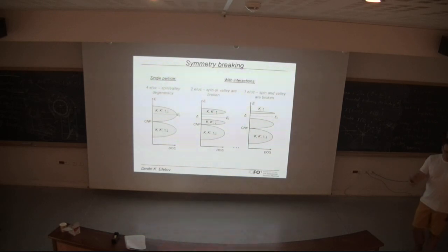Okay, but now with the picture demonstrated in the last phase diagram, one possibility would be that you could get gaps at 2 electrons per unit cell. That would be a picture where, for example, one band has 2 electrons per unit cell, and one of them is spin polarized, and the other is spin polarized in the other direction. So in principle, these bands could have different spin textures, but of course the other possibility is that they have different valley textures. This is an active field of study right now to really identify the ground states in these bands, but these are the possibilities.